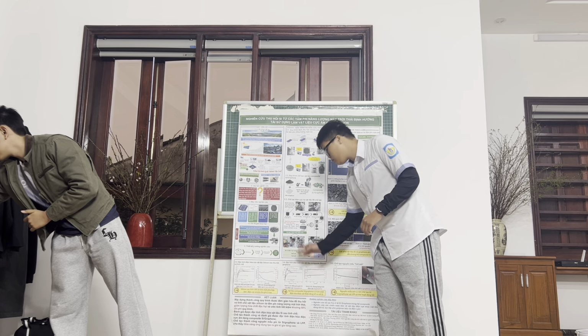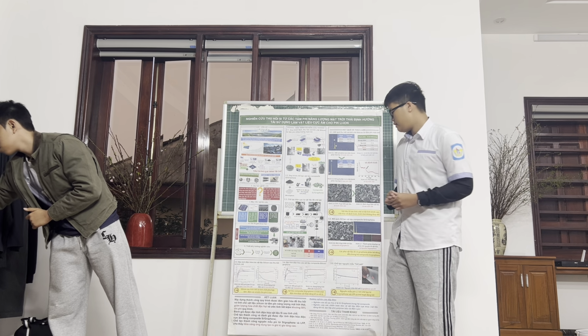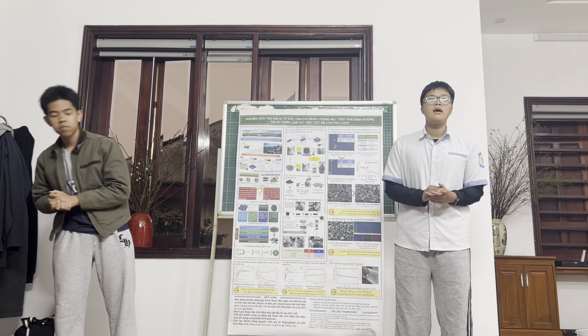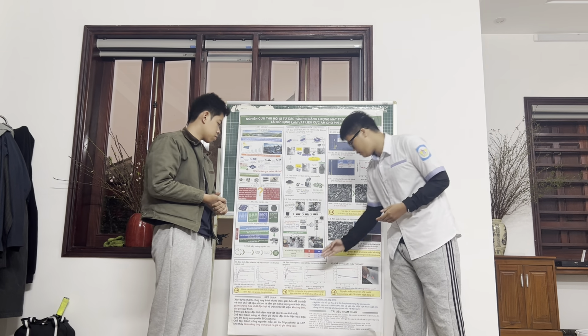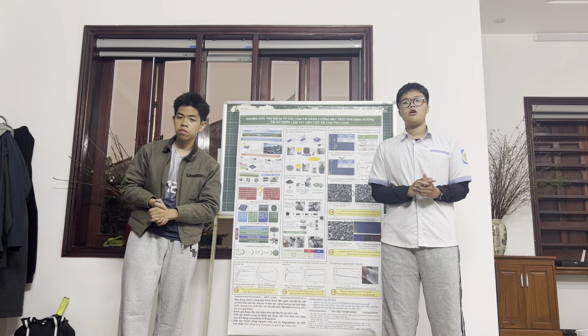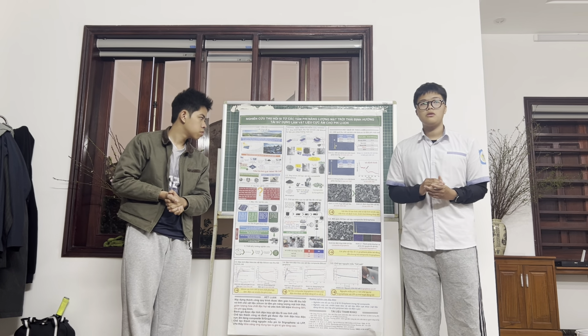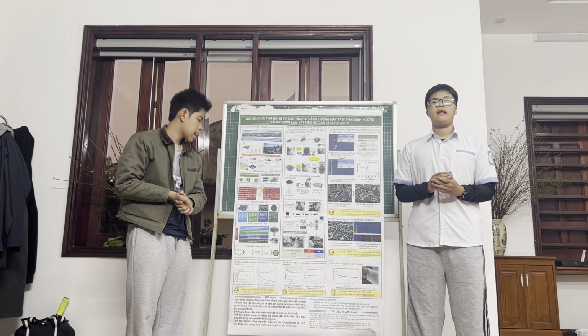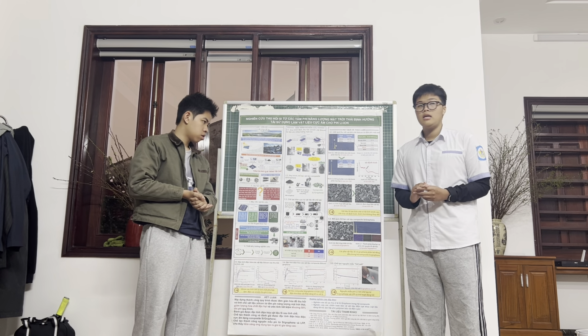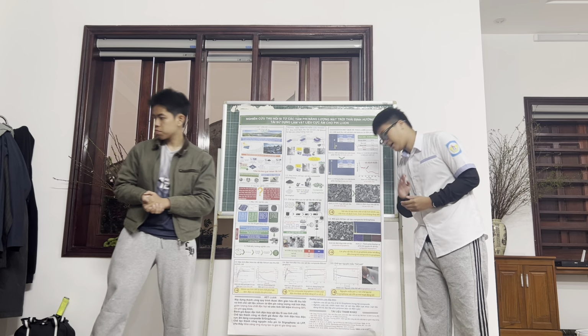CV measurements show similar oxidation and reduction peaks to those of silicon, and this composite has a specific capacity of around 600 mAh per gram and stable performance over 100 cycles, demonstrating an improvement in stability compared to pure silicon. Subsequently, a full cell was assembled using a silicon-graphene anode and LFP cathode. Charging and discharging at 0.5 C shows stable performance after 50 cycles, and the battery can power a common LED, highlighting